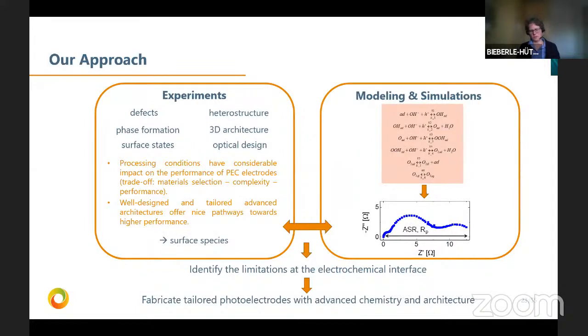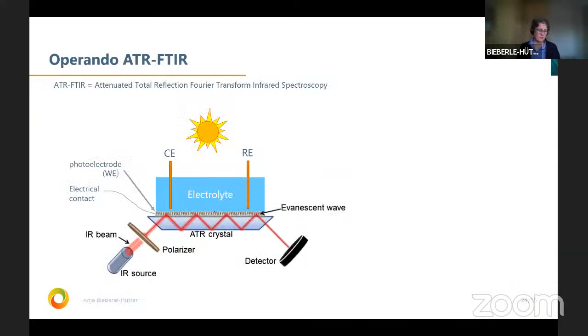What I have not talked about is surface species. And actually, when we would like to investigate the limitations, we should know these surface species. And there are different methods. We have heard them also already in this workshop. What we are using is operando ATR FTIR, attenuated total reflection Fourier transform infrared spectroscopy. What this technique is about is that you measure the infrared signature at the surface. So due to this crystal, you get these total reflections, and then an evanescent wave comes out on the top of your surface, and you can then measure an infrared spectrum very close to your surface.